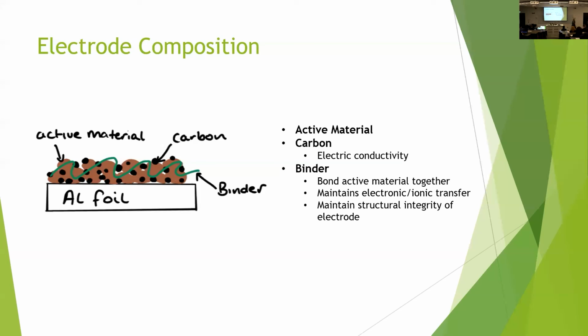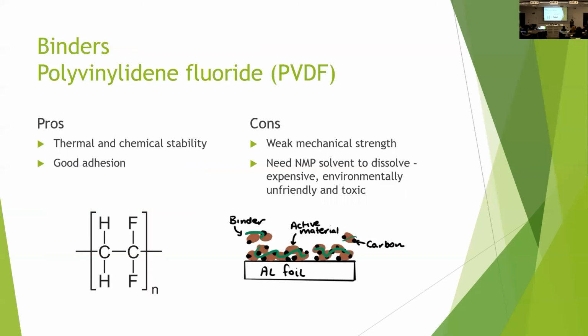Generally, how these electrodes are made is that you mix all your powders together and you put a solvent in, and then you cast this slurry onto your current collector. At least in this situation for cathodes, we use aluminium foil. Traditionally in lithium ion and sodium ion batteries, we use a PVDF binder. I'm not going to pronounce that. The advantages are that it's thermally and chemically stable, and it has really good adhesion, so it's really good for a binder to be sticky.